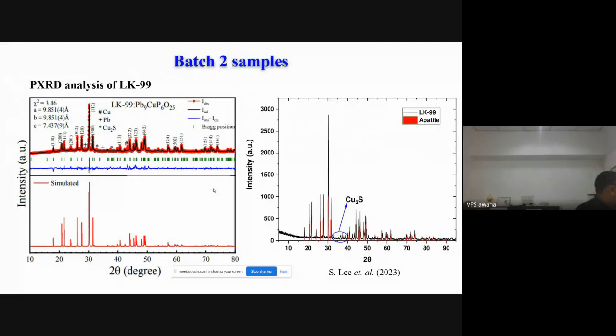This is the powder XRD analysis of our LK99, which is shown in the upper panel. And my student who does the DFT and all that simulated the LK99 pattern, which is shown in the bottom. And you will see, interestingly, that this time LK99 does not have copper and copper sulfide to that extent as it was earlier. Most of the lines are indexed very well. Of course, copper, Pb and Cu2S, because the equation itself says that it is not pure LK99, it's LK99 plus a composite of Cu2S, Pb and Cu.